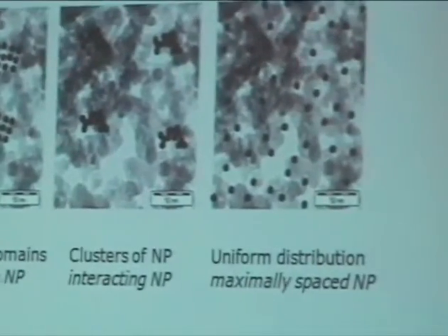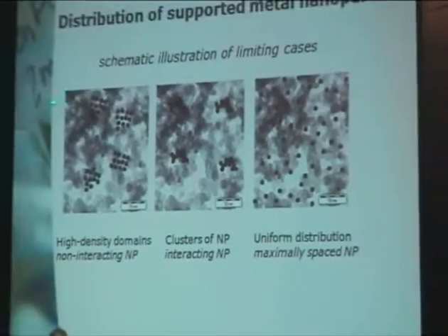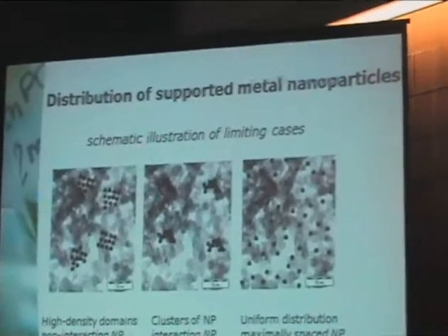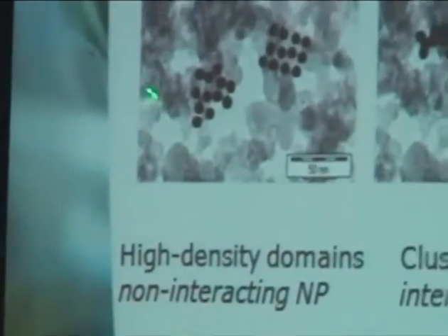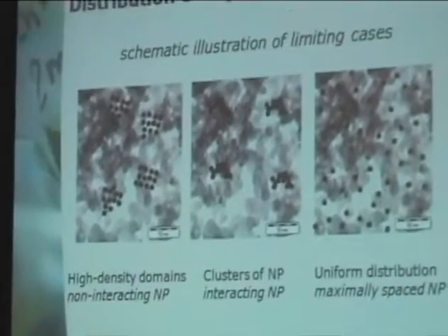And to illustrate what I'm hinting at is here a TEM image of a silica support. This is 50 nanometers, the scale bar. So the primary silica particles are about 20 nanometers or so, and I have drawn about 50 nanoparticles dispersed over this area of the support in three fundamentally different ways.